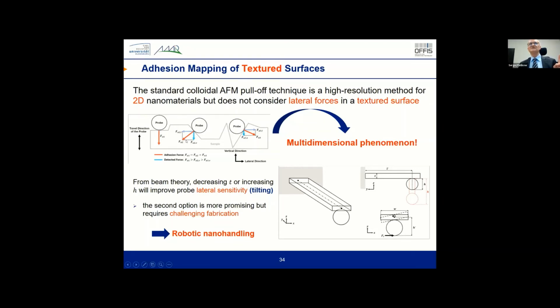It's a big difference. And to solve this problem, it is necessary to develop special tools which have lateral sensitivity, for example, by tilting the AFM cantilever. But it's not easy because the fabrication is very challenging to achieve this tilting. Normally you have just 1 degree of freedom in the AFM cantilever. Otherwise, the atomic force microscopy doesn't work. As simple as this.